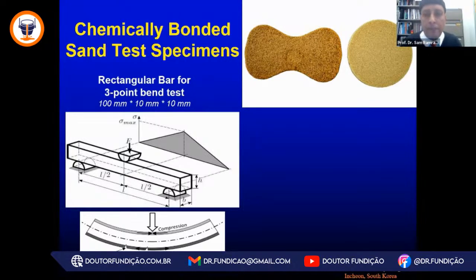Certainly, most people in the foundry industry are familiar with the dog bone specimen. And I have the dog bone specimen. From the dog bone specimen, we only get mechanical data. That is the problem. But that is not the only problem. This specimen has this narrow waist, we could call it. I like to call it the sexy part, but it sometimes doesn't always break there. It breaks up at the shoulder, it sometimes breaks lower down at the waist. And for that reason, we have higher variability test to test in the mechanical test.